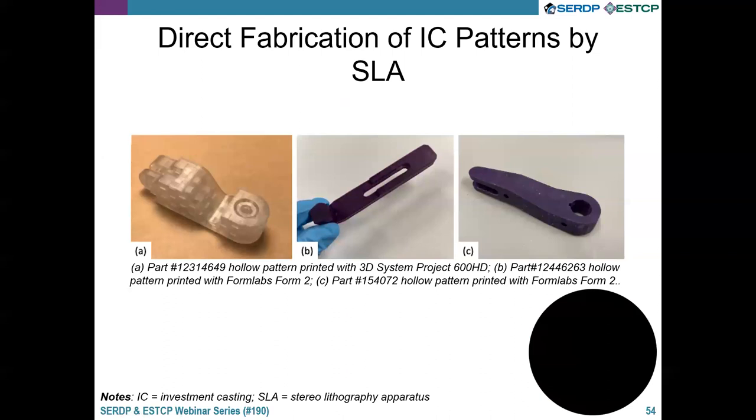really necessary to print those patterns in a hollow structure to avoid cracking of the casting molds during the later burnout process. The hollow structure of the patterns can reduce the amount of material used and avoid cracks in the ceramic shell that typically are caused by the polymer expansion during the burnout process while maintaining sufficient strength of the patterns. So once those polymer patterns have been created,